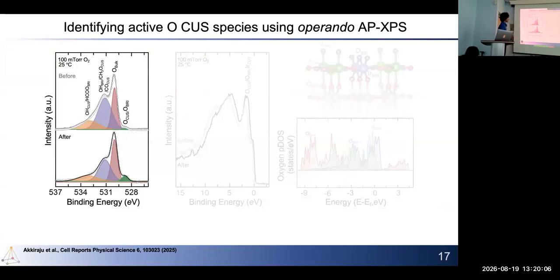For those who are familiar with XPS, this is what an oxygen 1s spectrum would look like from an XPS. You would notice a really peculiar feature in this XPS spectrum at 529 eV. Typically, as you would expect, the earliest peak would be a bulk oxygen peak, and every other oxygen peak would be towards the left of it, related to either hydroxyls, carbonaceous species, whatnot.